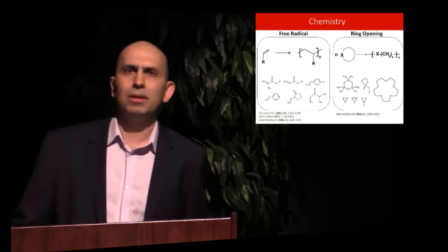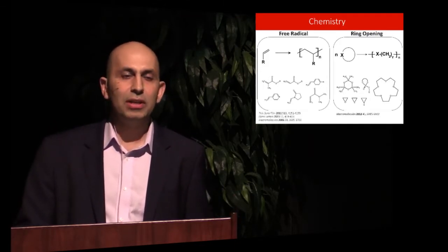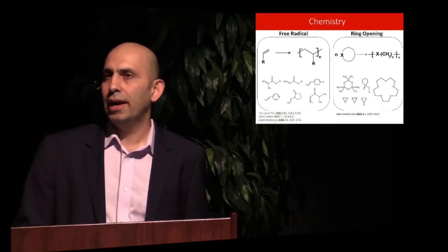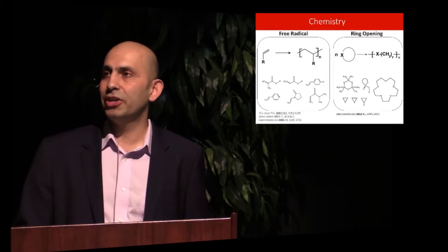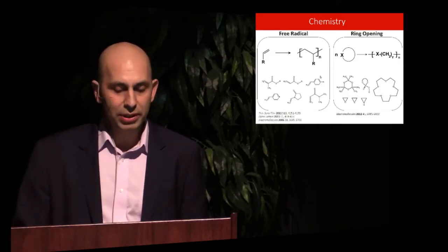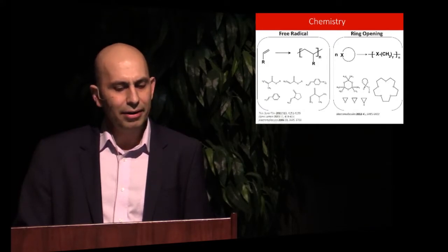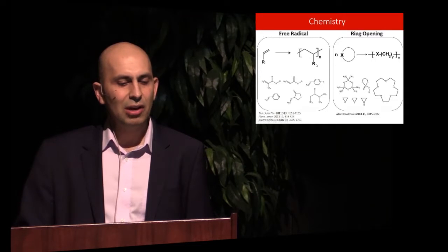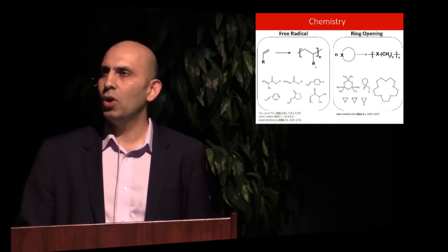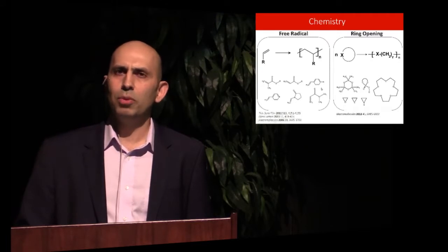So this is the schematic of the filaments located inside this chamber. The gas molecules come in here, the initiator breaks on the filament, attaches to the surface along with monomer, and polymerizes on the surface. And there is a bunch of different chemistry that has been explored in the past 10 years. They are pretty interesting in terms of free radical polymerization, ring opening polymerization, and I have contributed to oxidative polymerization, which is also a very interesting family of these polymerization techniques. So you can think about R, the side chain of this monomer, which is a vanillin monomer, to be anything. So we can adjust the surface any way you want because we can bring functionality to a surface which is robust because it's a polymer.